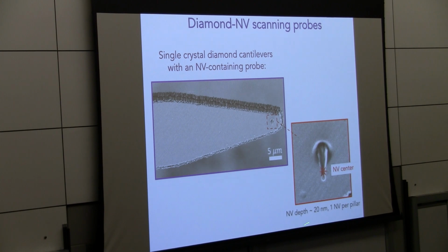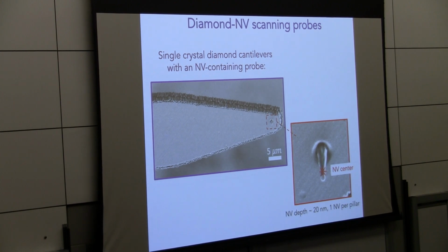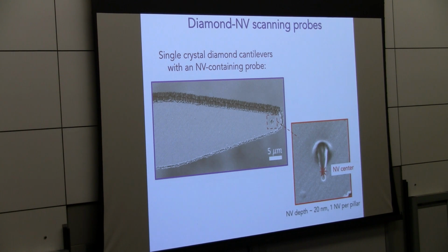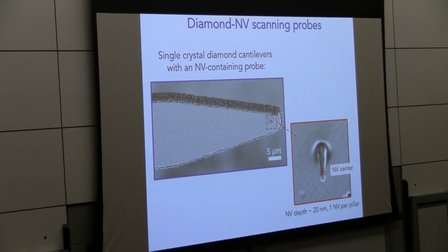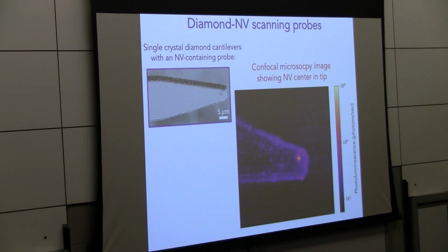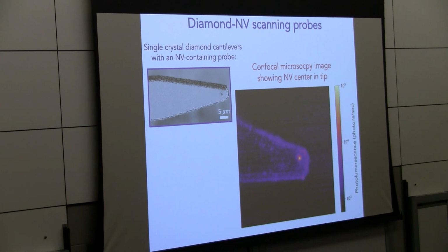The data that I'll show you today, the NVs were about 20 nanometers away from the surface. And we can pick the pillars that have one single NV per pillar to really maximize their spatial resolution. And then confocally, one can take a green laser and scan it over this cantilever, monitor fluorescence as a function of laser position, and one sees a very bright spot right here, which corresponds to the fluorescence of a single NV center. It's another nice benefit of these pillars, in addition to being able to position our NV centers close to the sample under study, they also help waveguide the light for enhanced collection efficiency into our collection optics, and so you can see we get on the order of 10 to the 5th photons per second.